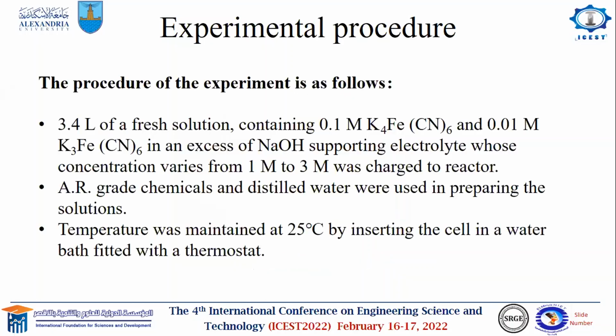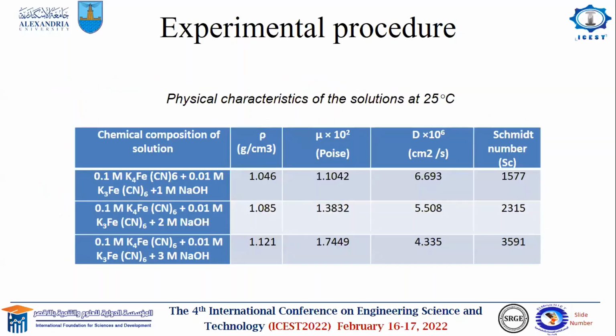First, I prepare 3.4 liters of the fresh solution containing 0.1 molar potassium ferrocyanide and 0.01 molar potassium ferricyanide in a large excess of sodium hydroxide, whose concentration varies from 1 molar to 3 molar. Temperature was maintained at 25 degrees Celsius by inserting the cell in a water bath fitted with a thermostat. Physical properties of the solution are obtained from previous studies to calculate Schmidt number.